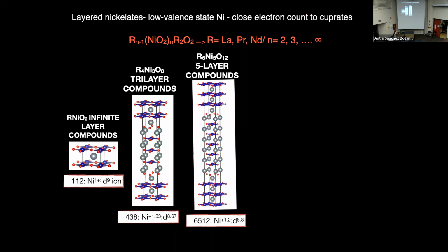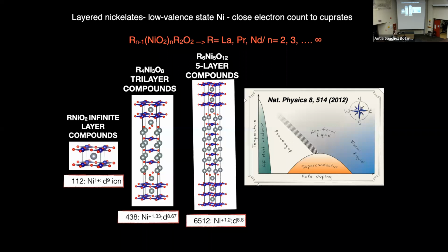Now, before I move on, let me repeat the same type of ionic count that I did for the infinite layer material for the other two compounds so that we can see where they sit in the cuprate phase diagram. Remember, for the infinite layer material, what we have is a nickel 1+ ion, that is a pseudo copper 2+. If you repeat the same exercise for the tri-layer compound, that is this 438 material, what you end up having is a nickel 1.33+, that's 8.67 d electrons per nickel on average. For the 5-layer compound, that is this 6512 material, what you have instead is a nickel 1.2+, that is a d8.8 ion.